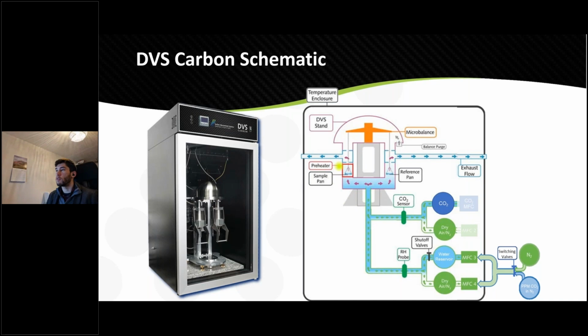This is where the sample is, the local heating. And we have the two mixing sides. We have CO2 mixing on this side with a patented speed of sound sensor to know exactly how much CO2 is being generated. And on this other side, we have a water reservoir, which mixes a wet and dry stream of nitrogen, also with a probe, to make sure you know exactly how much water is being introduced. These two streams are mixed together to generate the flow that the sample is seeing.